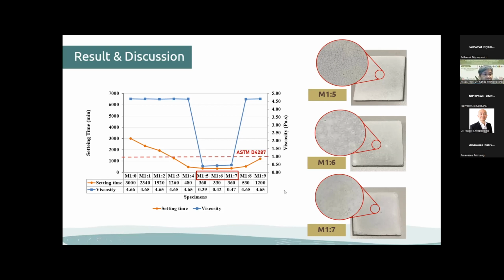In the experiment, we selected the slurries M1.5, M1.6, and M1.7 for spraying on the cement mortar. The coatings with M1.5 and M1.6 had cracks across the coating surface after drying, due to the slurry having a higher water content. The M1.7 specimen had some cracks around the edge. It had the least cracking due to the lower drying shrinkage. In M1.5 and M1.6 there was more sodium hydroxide in the slurry than in the M1.7 specimen. The M1.7 formulation was then selected for further investigation of the technique for coating the slurry.